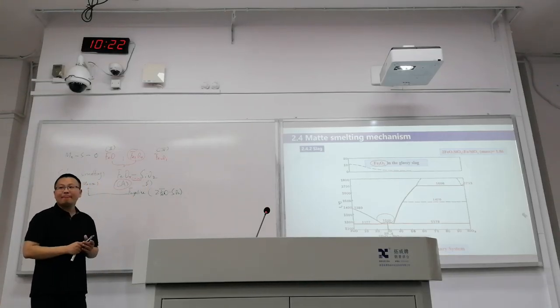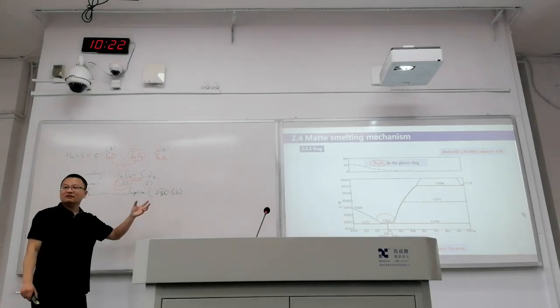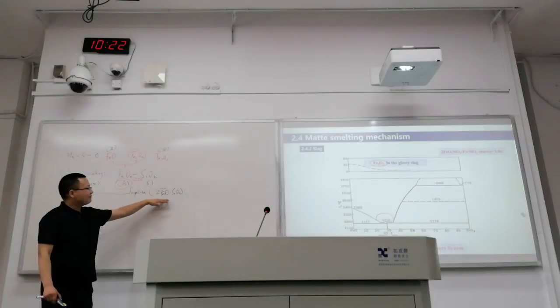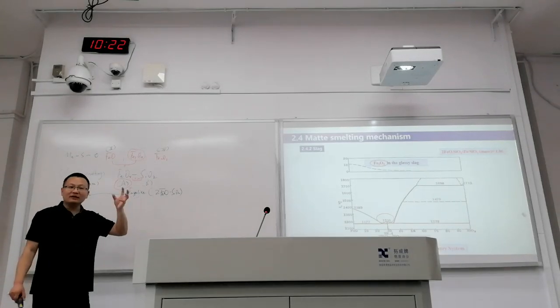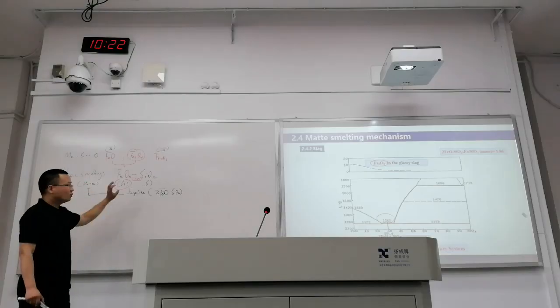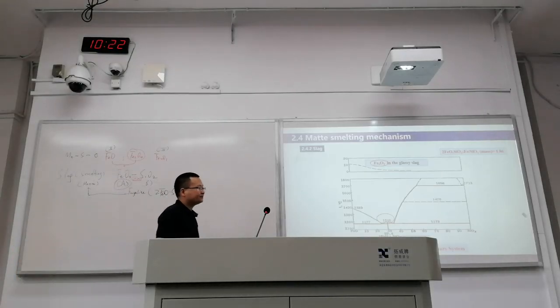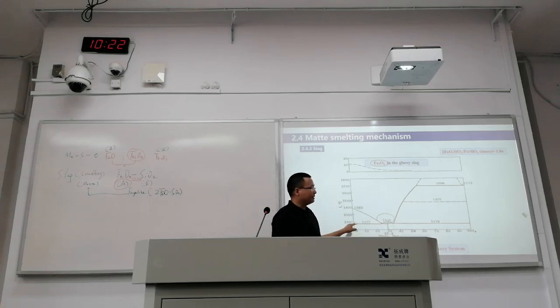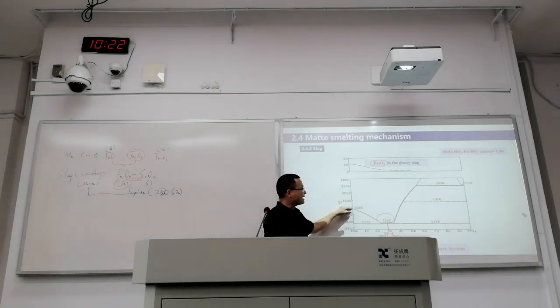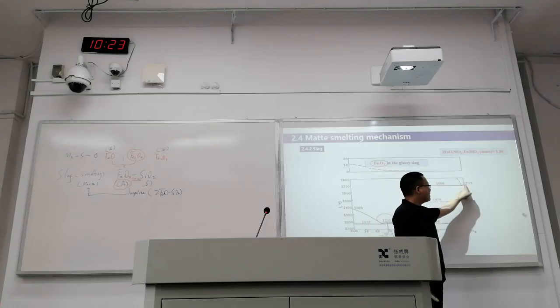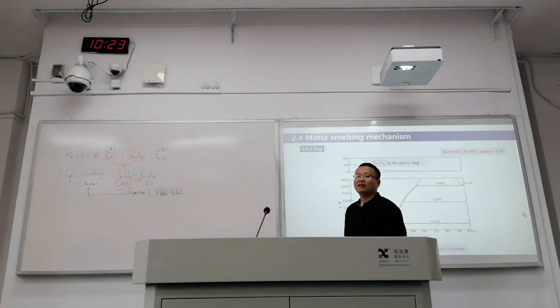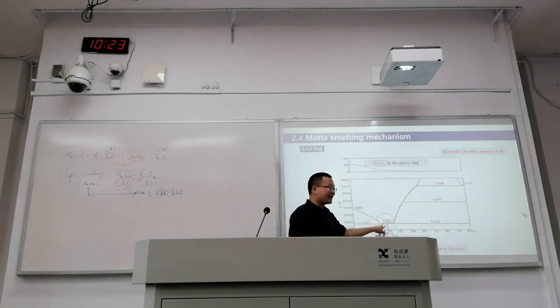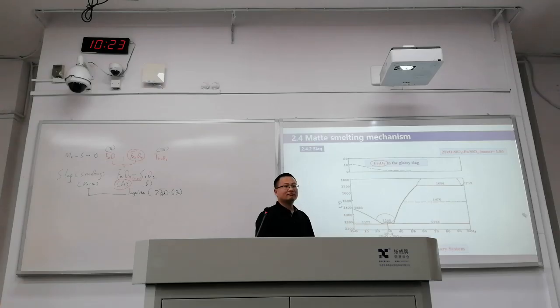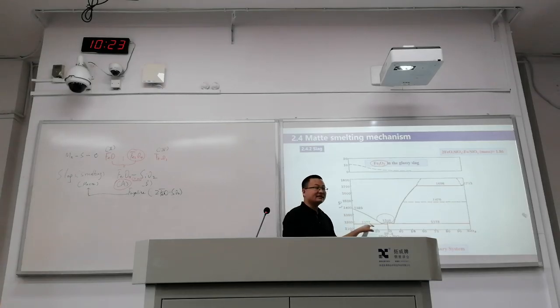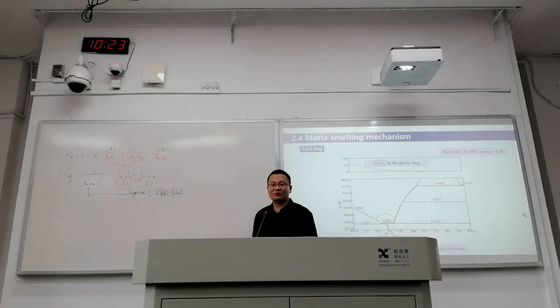Fayalite. So this is a mineral, and you are getting XRD peaks. This is a major component in the slag phase. So we have this name, fayalite slag. So we know the melting temperature for ferrous oxide is 1389, something like that. And we have silicon oxide, the melting temperature is 1713. But the lowest temperature when we are getting liquid will be around 1177. So that's good, a reasonable temperature for us.